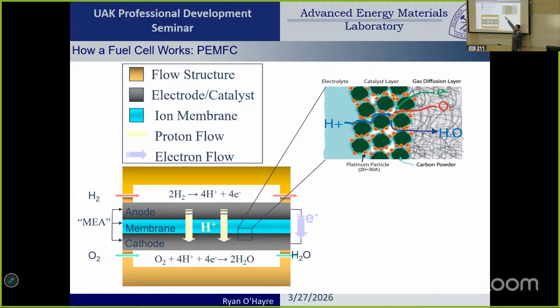And then right at the interface between that porous electrode and the electrolyte, we put a thin layer of our catalyst. And typically for a polymer fuel cell, that catalyst is these super fine carbon powder particles. And decorated on the surface of those carbon particles are even smaller, little tiny platinum catalyst particles. Now we could just put a whole bunch of platinum right there and it would work even better, but that would be super, super expensive. So the name of the game here is to try and thrift the platinum and use as little as possible, get the biggest bang for your buck. So this kind of structure works really well because we basically have just a tiny little bit of platinum, but it's all used very, very efficiently.